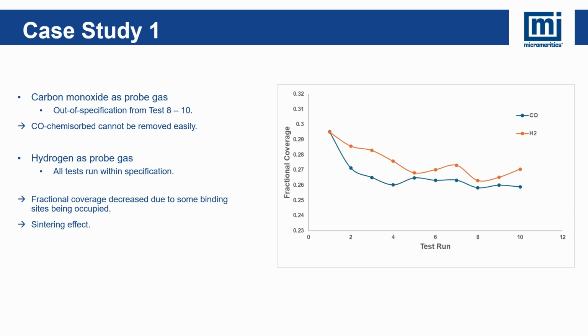The first case study was conducted utilizing static chemisorption. The sample was prepared in situ with the procedure that was mentioned previously. 2 experiments, each consisting of 10 test runs, were conducted. The first experiment used carbon monoxide gas. The second experiment used hydrogen gas. The results from these 2 experiments show that the dispersion values decrease with repeated use of the same sample.